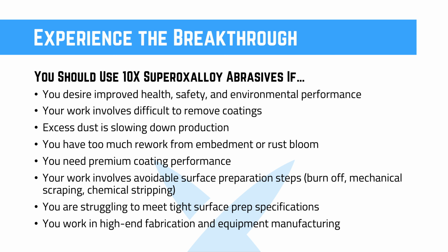We have gone into aluminum oxide applications many times now, and we have encountered alumina zirconia. We have encountered silicon carbide, as we showed you in the presentation, and we are going faster, and we are leaving a cleaner surface. And the reason is that energy delivery. The other abrasive particles that are not produced in a controlled environment have weak planes in them where they tend to break. And now, silicon carbide doesn't break as much as, say, a slag or crushed glass would. It's not nearly as friable. But what we're finding is that it does not deliver as much energy to a surface as our superoxalloy does. And we're seeing it all the time. We've come to expect it.